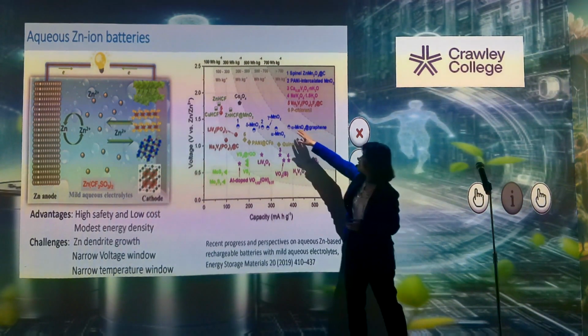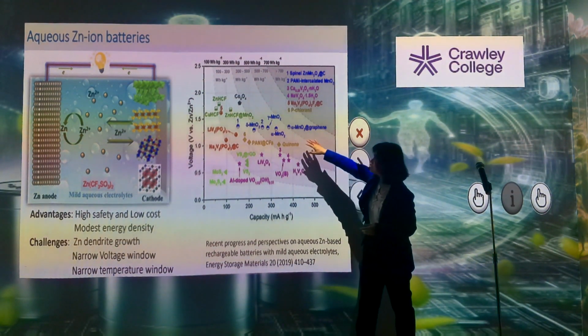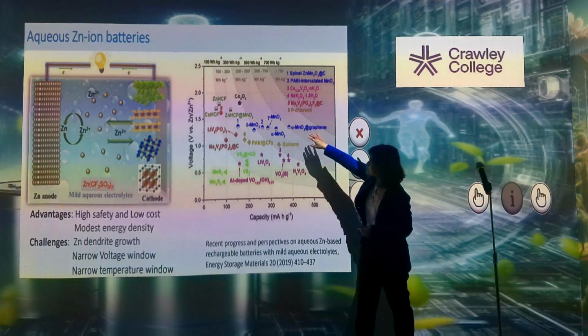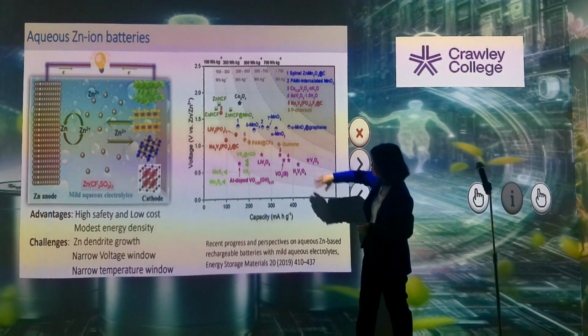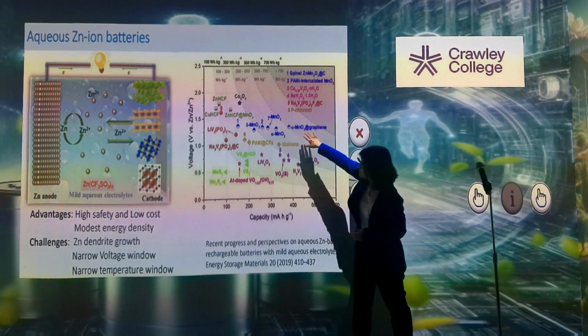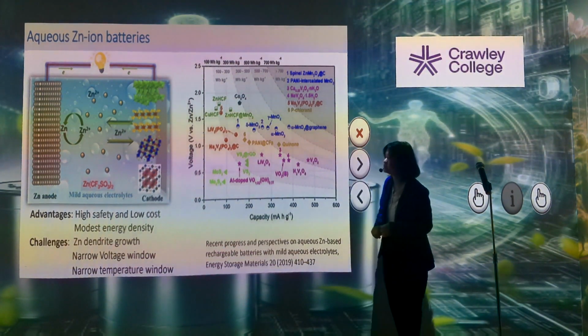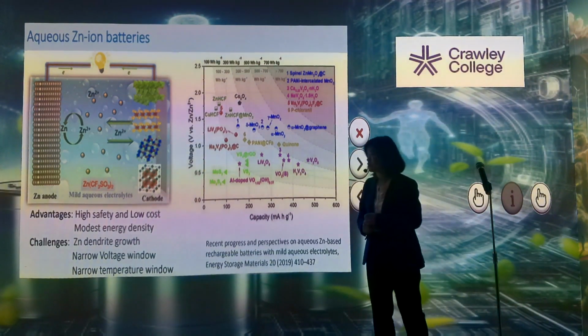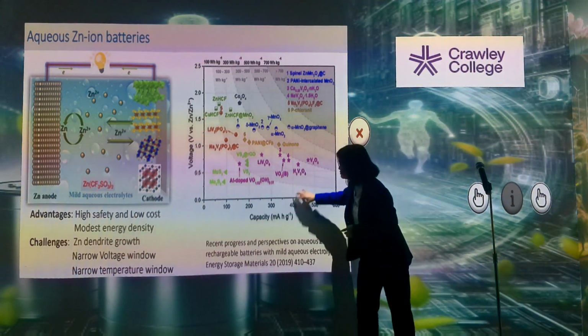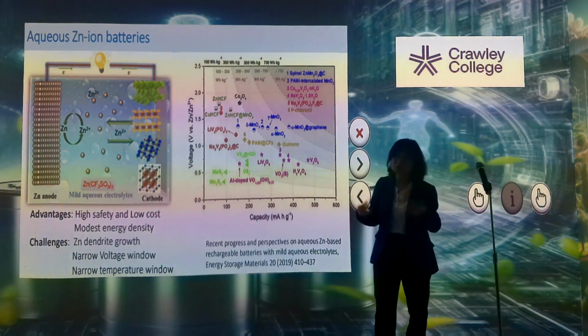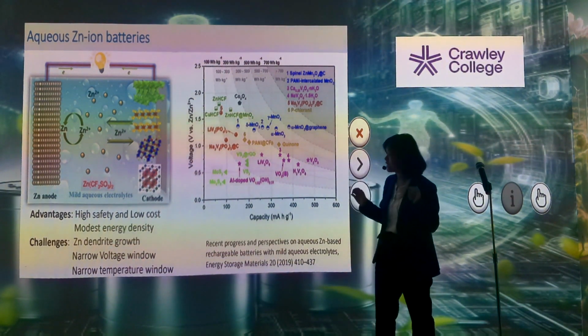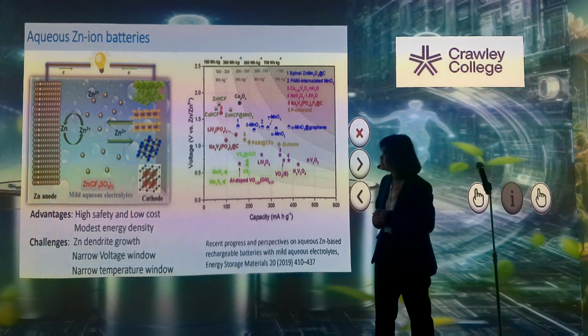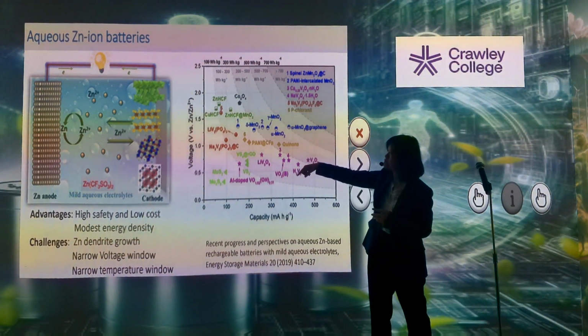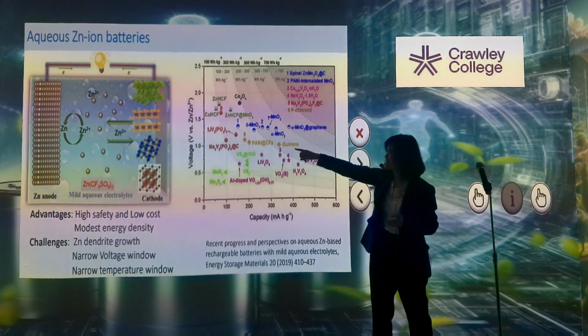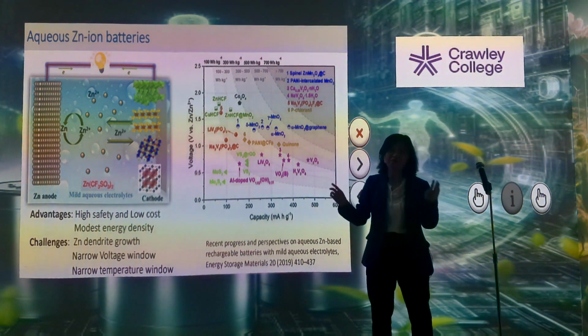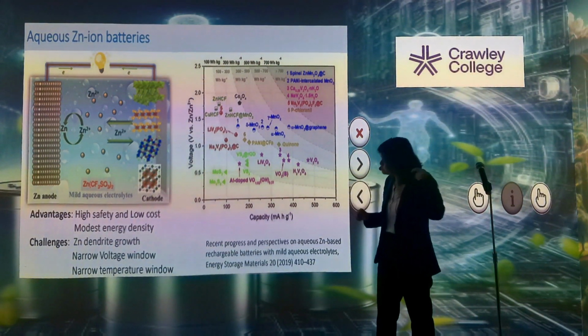You can see probably the manganese oxide one is probably the most promising because it has very high storage capacity, and also good voltage potential. The challenge is though, when you look at the capacity, then you know that this type of battery can have quite good storage capacity. The challenge is, similar to lithium metal, the zinc metal has dendrite growth there. So you want to prevent that.